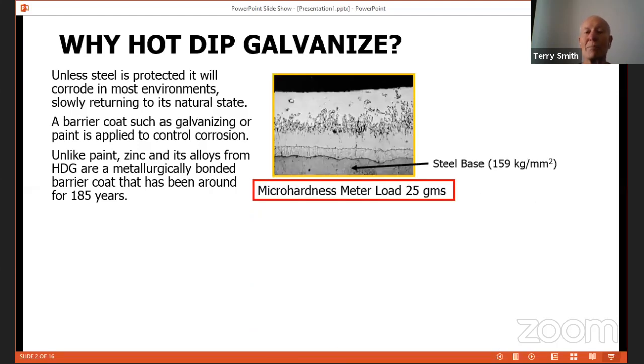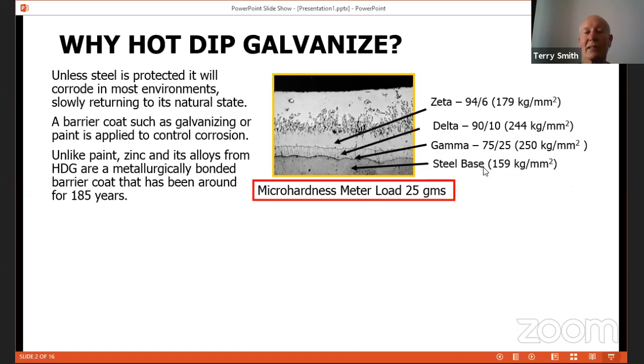That's the typical micrograph of the coating. You can see the various iron-zinc alloys, the steel base being 159, and the iron-zinc alloys above, the gamma, delta, and the zeta layer, which you can see are harder than the steel itself. So it gives you tremendous abrasion resistance. It's normally overcoated with a pure zinc layer on the outside called the eta layer.